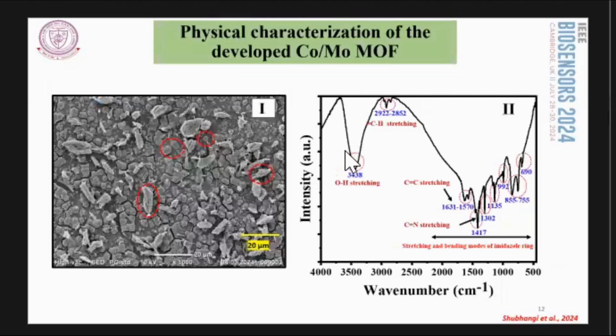So we synthesized the cobalt molybdenum MOF through the electrodeposition method by optimizing the potential and the deposition time. And we were successfully able to synthesize the bimetallic MOF, which we confirmed using various physical and electrochemical characterizations, primarily the FTIR studies, where we could get the stretching and bending modes of the imidazolic ring, that is the linker moiety in the MOF structure.